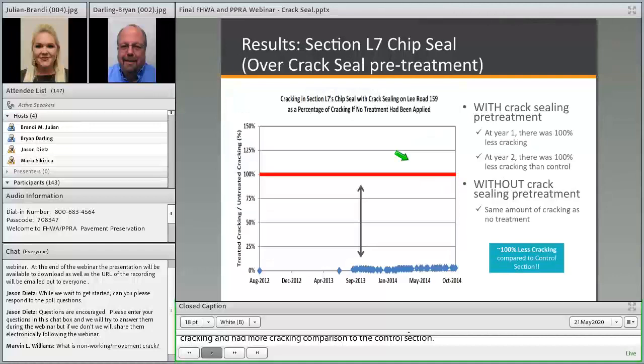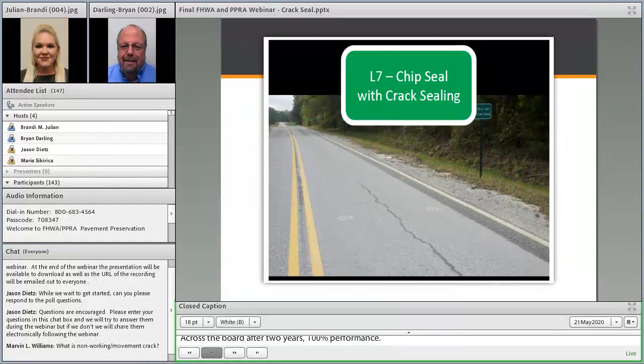So what we looked at next was the section where they came in and did a crack sealing pre-treatment first on the cracking, and then put a single layer chip seal down. And you can see here the outstanding performance. Across the board after 2 years, 100% performance. So a huge swing there. Without crack sealing, it basically lost all benefit after 2 years. And just by crack sealing first and then putting that chip seal down, it was still performing at 100% after 2 years. So great data there, showing that crack sealing helps the effectiveness of other surface treatments.